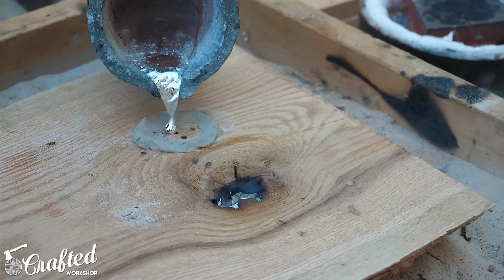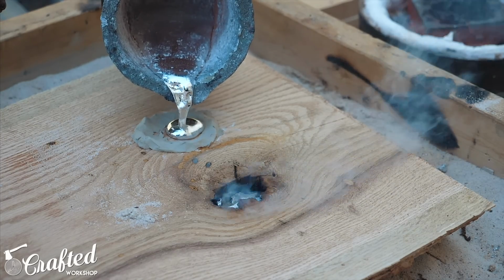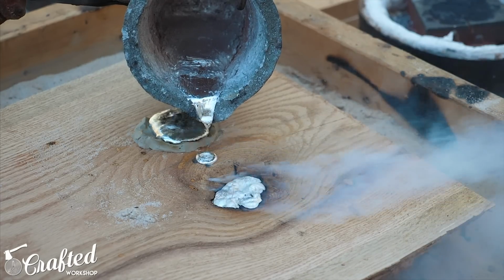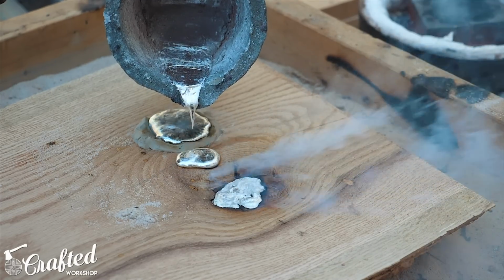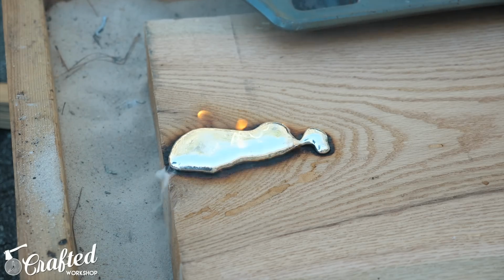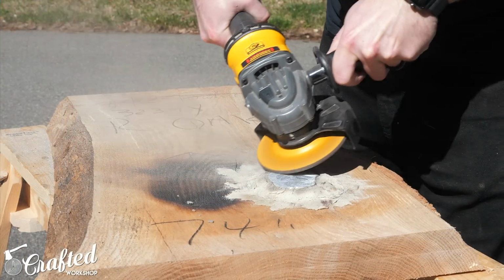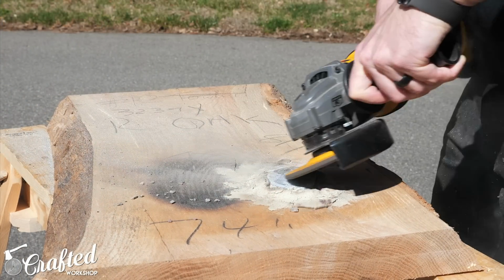We also experimented with filling some of the bug holes and cracks with aluminum, but it was just too thick to flow into these holes and just kind of sat on the surface of the slab and caught it on fire. After flipping the slab over, we saw where all that extra aluminum had built up on the surface,